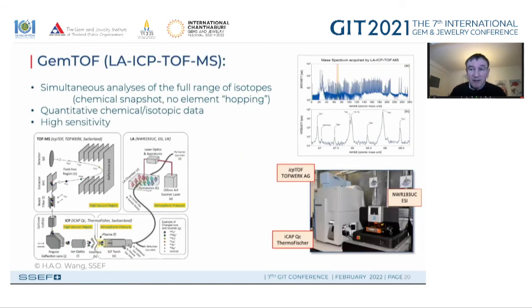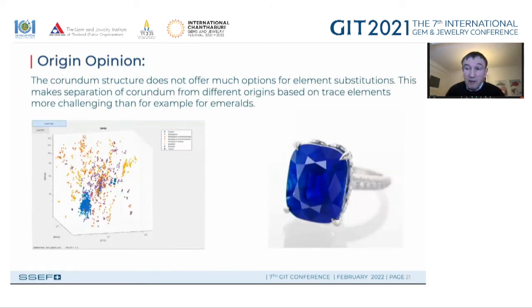If you want to have access to chemical data, then at SSEF we use an instrument called GemTOF. This is actually laser ablation inductively coupled plasma time of flight mass spectrometry. And different to the more common quadrupole mass spectrometry, where you actually have to pre-select elements which you want to measure, and then you have a peak hopping mode, so you measure one element and then the next and then the next, with GemTOF, you have a snapshot. You have the full spectrum of all isotopes at the same moment, and by this you have much more information for sure. Now with this instrument, we are analyzing corundum and other gemstones also to find answers about origin.